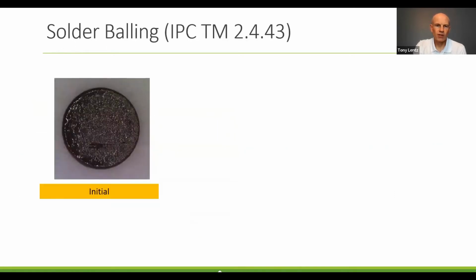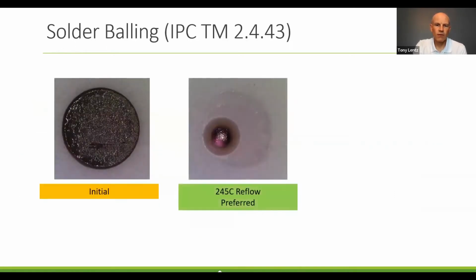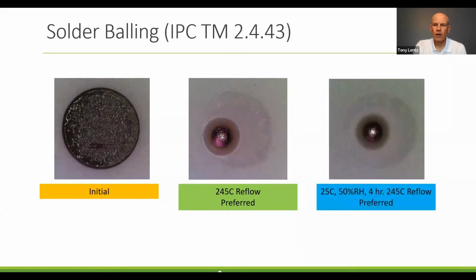Here's an initial picture of the solder balling test. Here's after initial reflow at 245C, almost no solder balls in that flux ring. And then here's a picture of the same test after it was stored for 4 hours at 50% relative humidity and then reflowed. Again, preferred results in these two tests.